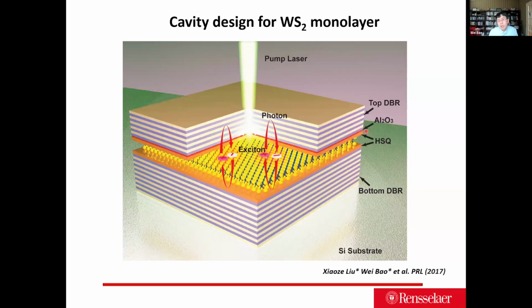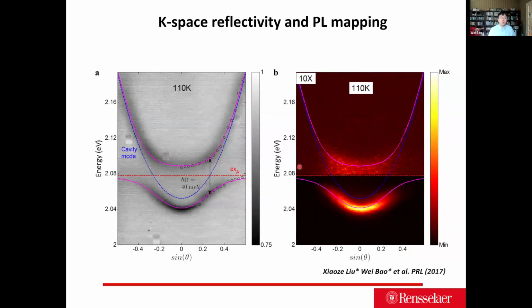And to further protect the material during sample fabrication, on top of the HSQ we also deposit atomic layer deposition aluminum oxide to further seal the sample. In this way, any harsh deposition on top will bombard the aluminum oxide instead of the two-dimensional material and generate defects. With this method, at the very beginning, we see really nice dispersion and a Rabi splitting as large as 40 meV, and the line width is as small as 8 to 9 milli-electron volts. And this is under white light reflectivity.